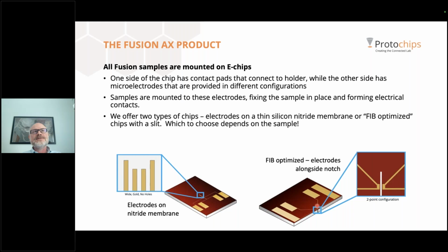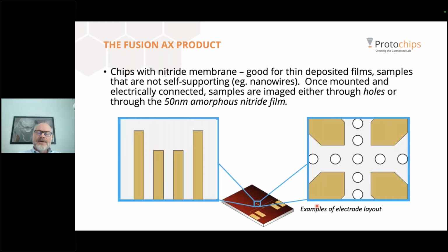And which you want to choose depends on the type of sample that you want to analyze. Now, for chips with a nitride membrane, like shown here, these should be chosen for samples that are not self-supporting and need the nitride film underneath as a support. Examples of these types of samples would include thin deposited films that need to be deposited on a substrate, or small fragile samples like nanowires. These samples are imaged either through the 50 nanometer thick nitride film or through small holes that are patterned in the nitride. And we'll take a look at an example of that type of analysis in a moment.